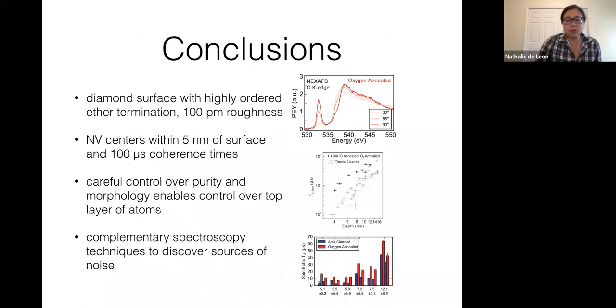So just to conclude this first part of the talk, we've been able to use this feedback loop between surface spectroscopy and NV-based spectroscopy to figure out how to make a new diamond surface termination with a highly ordered ether termination and very, very smooth surface morphology. This allows us to make NV centers within a few nanometers of the surface with coherence times that we can dynamically decouple out to about 100 microseconds.